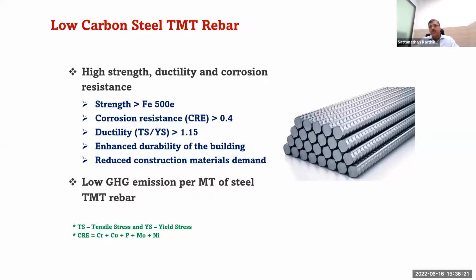It looks at various properties of the steel. Typically we look only at the strength of the steel, but we are also looking at how ductility has been maintained. This is a very, very important parameter as part of the steel utilization. Because from the durability point of view, more than the strength, the ductility matters a lot. So the ductility, which is the ratio of tensile strength to yield strength, we need to look at. It should be more than about 1.15 here. And also we are looking at the corrosion resistance property, because this is one thing which reduces the life of the building.